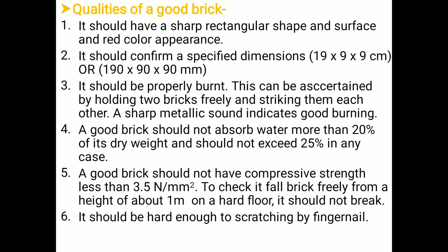After striking each other, it gives a sharp metallic sound, which indicates good burning. If you observe a sharp metallic, ringing sound, then we can say it is a well burnt brick. And if the sound is dull, then we can say it is an underburnt brick.